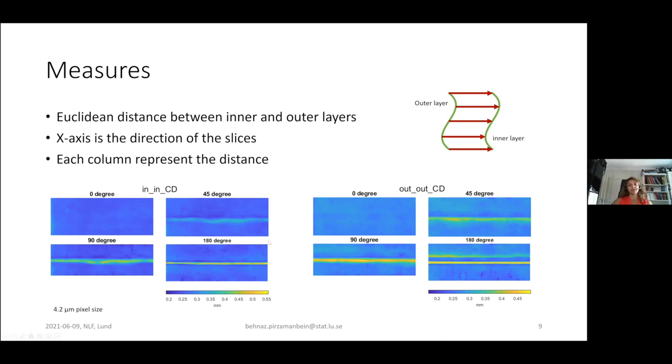If you look at the images on the left side at the bottom, this is where aluminium was the inner part of the layer, and you can see that aluminium has clearly formed a delamination in the center of the crease line, going from 90 degree to 180 degree. It's quite obvious. And then in the other material, when the clay was the inner material, we get two different delaminations around the edges of this crease line. So in this way, we can characterize the property of the material when we bend them, and we can measure how they are different from each other.